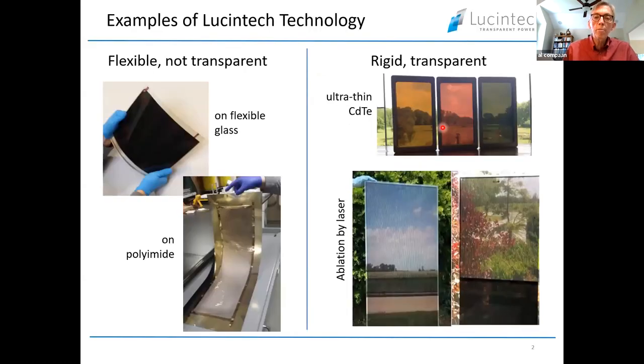So just to give a pictorial overview of what we started out, we formed the company Lucintech, with the original idea that we'd work with flexible solar cells, not transparent. The first substrate material that we worked on was polyimide. This is actually on Kapton, a DuPont product. This is about a 5 foot long deposition and about 1 foot wide. We've also then transitioned to use a flexible glass. This has been laminated, but this is on a flexible glass from Corning, the Willow product, which actually works very, very nicely.